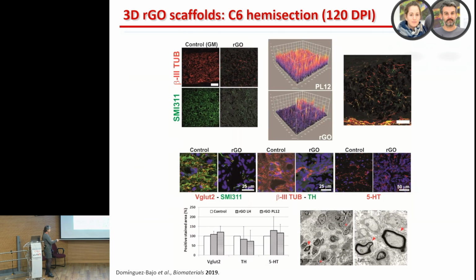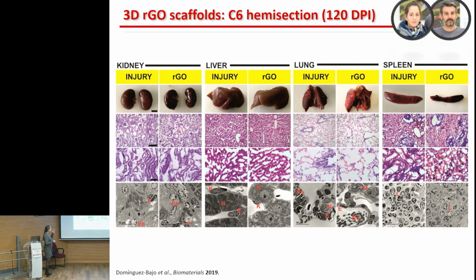And we also found neurites. As you can see here, this is again the scaffold, and you see a lot of reddish, whitish, and greenish color. That means different markers of neurites. So our scaffold was also colonized by neurites coming from the borders of the injury. And they were actually myelinated, as you can see here, because they were more mature for the transmission of the electrical signal.